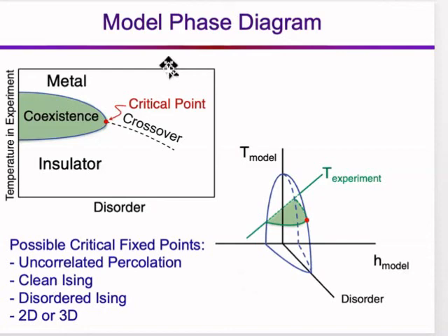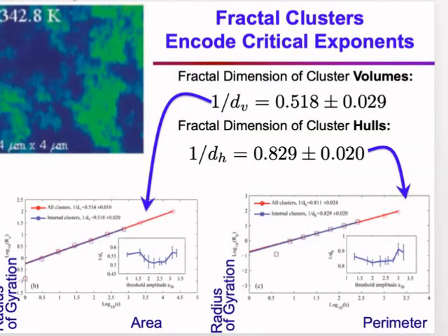What we have studied here is to take advantage of the lovely spatial resolution available in these probes. Our previous speaker showed an example of tuning by temperature in order to get a critical exponent, right? The shape of that magnetization as it comes down in temperature gives you the critical exponent beta. Here, these spatially resolved probes offer a different way to get critical exponents out. Rather than tuning temperature or tuning magnetic field, you can, in a single shot, effectively think of your length scale as the tuning parameter that'll allow you to get a critical exponent out.